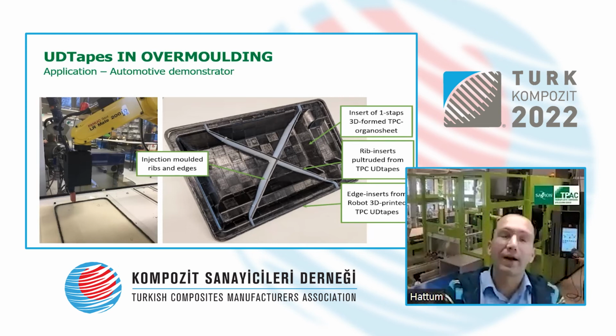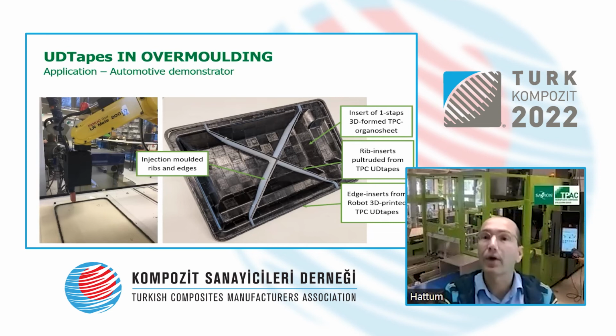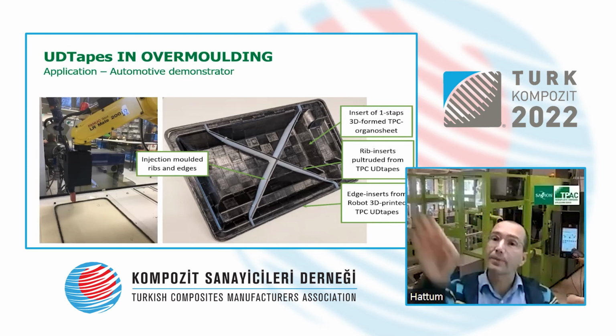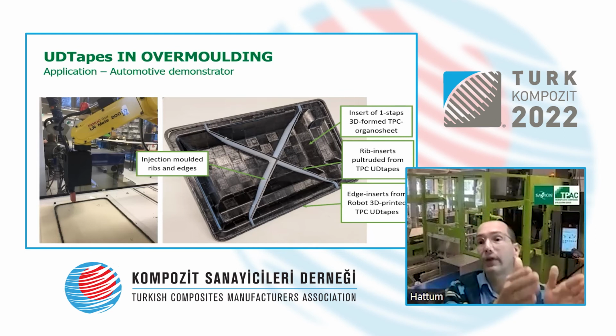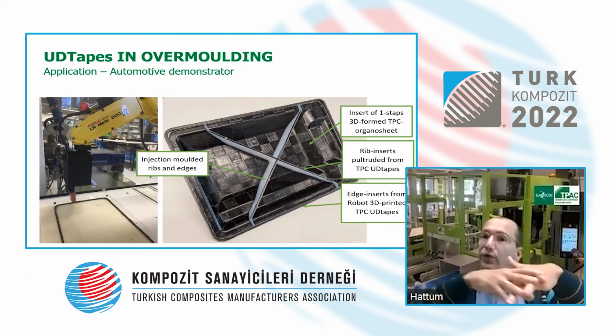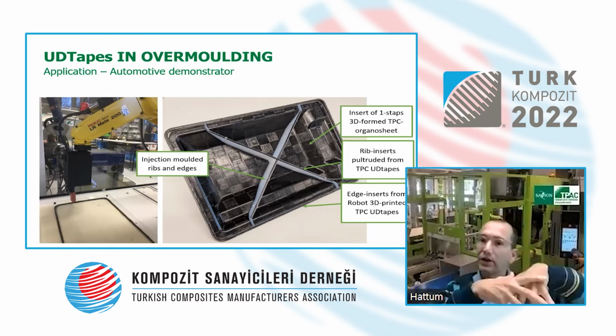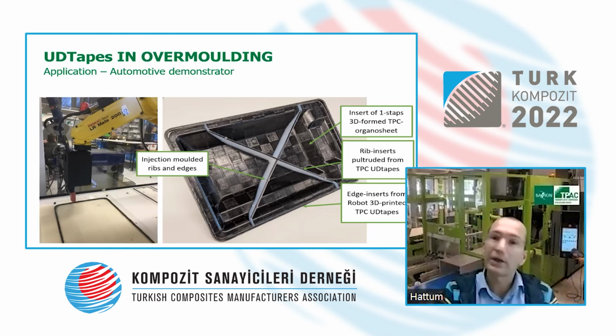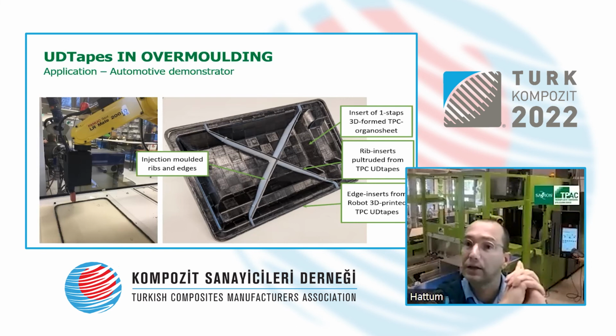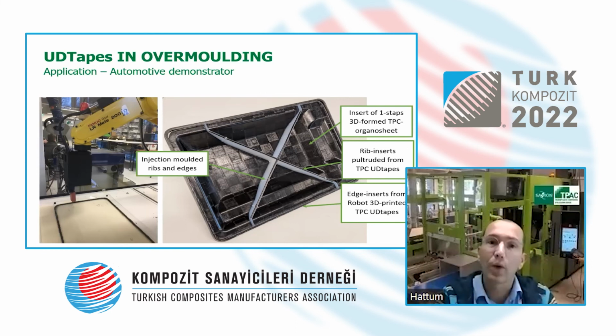Just to show what this has accumulated in. So right now in our lab, we cover the whole development scope from base materials together with a tape supplier. We can make any kind of continuous fiber reinforced tapes that then we can locally weave either in organo sheets, the 0/90 pre-consolidated sheets, or we can make 3D prints. And in the end, we can make, well, a completely integrated part like this in the machine you see behind me. Typically 1 minute cycle.